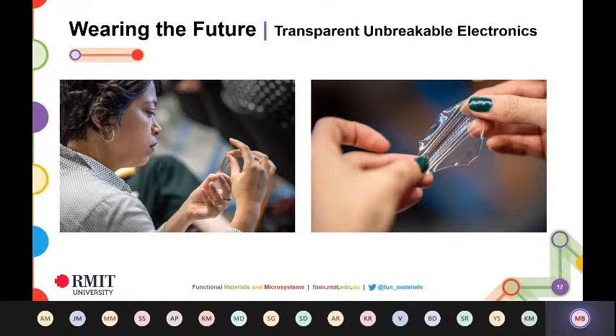There was some interest from defense because obviously these are gas sensors, so it's nice to imagine them in a wearable context for gas sensing applications. And also because they are good UV sensors, they are quite useful in the sense that Australia has quite a high incidence of skin cancer. So trying to understand your UV exposure levels on a day-to-day basis, it is quite useful to have a UV sensor to do that. Those are some of the end applications we had in mind when we spoke to quite a few industry partners. But as you can see, the materials are really thin and transparent, and we achieved what we set out to achieve, which was transparent, unbreakable electronics.